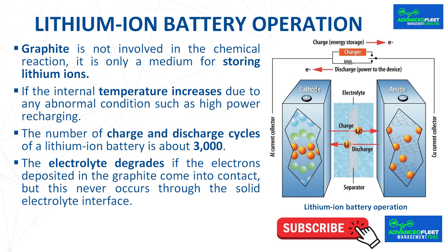When the battery is charged for the first time, lithium ions move through the electrolyte and the solvent molecules in the electrolyte cover the lithium ions. When they reach the graphite, the lithium ions along with the solvent molecules react with the graphite, forming a layer called the solid electrolyte interface (SEI), which prevents any contact between electrons and the electrolyte, preventing its degradation. In the process of forming the SEI layer, 5% of the lithium is consumed. The thickness of the SEI layer is optimized for maximum cell performance.